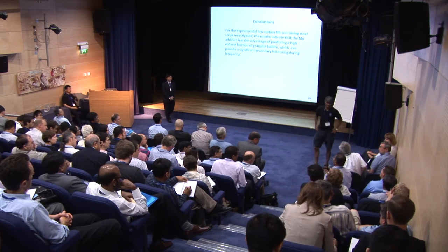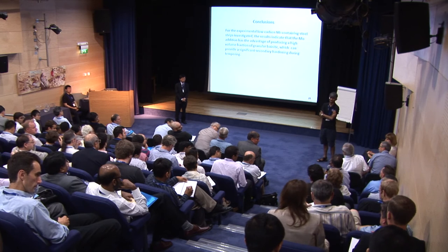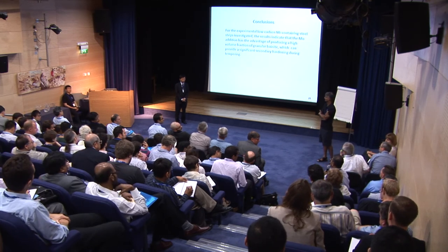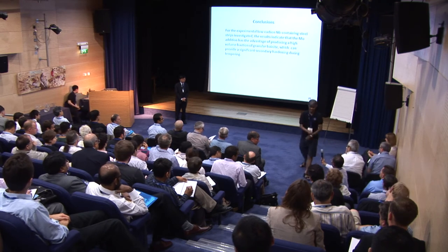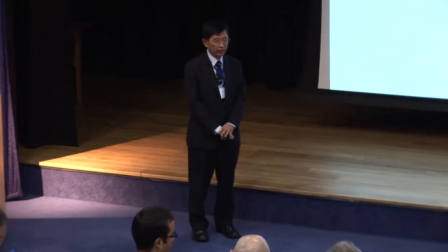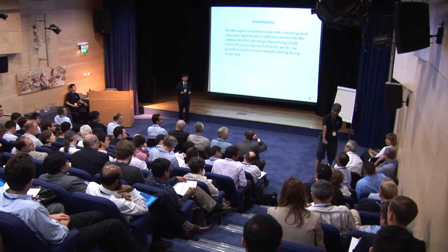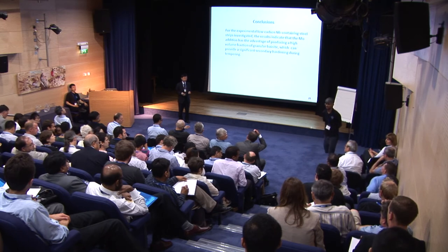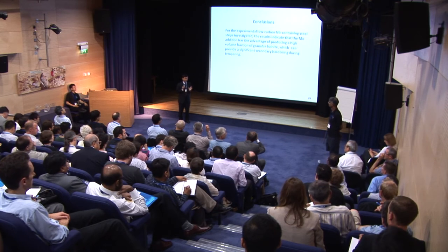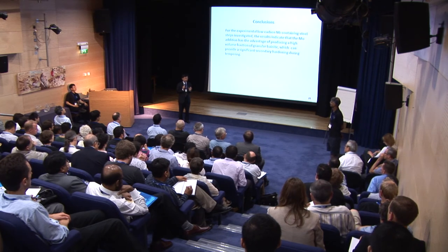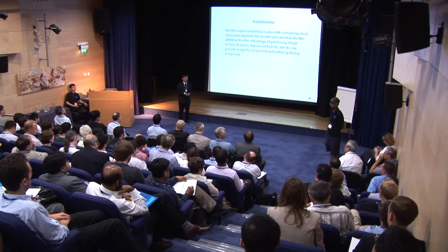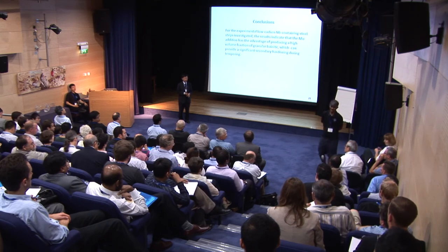You have a lot of MA constituents also. So are carbides forming in granular bainite or in those MA constituents? How would you differentiate this? It's very easy, because in the bainite region we can see the subunit, as I showed you, and it's a subgrain, and it's completely different from the MA phase area. Even after tempering, because tempered martensite would look similar also. Tempered martensite always gives you coarse carbide. We can discuss later.